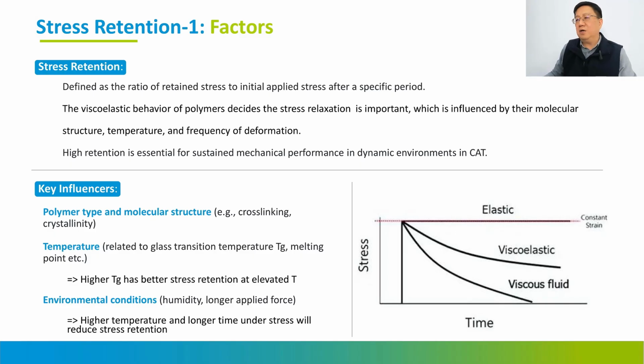For retention, you can see these figures. If the material is elastic, hopefully it can provide a constant constraint, so the stress will be the same. But that's almost impossible for all materials. If the stress loss can be kept as low as possible, that is good enough. So if you select a good material, such as higher Tg, more branched polyols, and more crosslinking areas, then this kind of polymer will give you high stress retention.